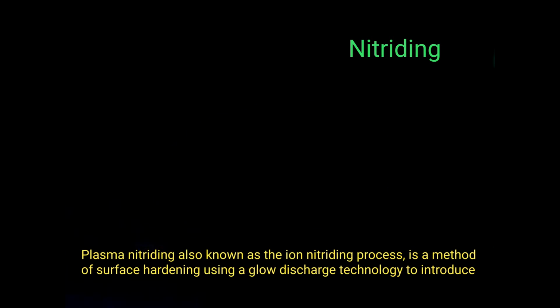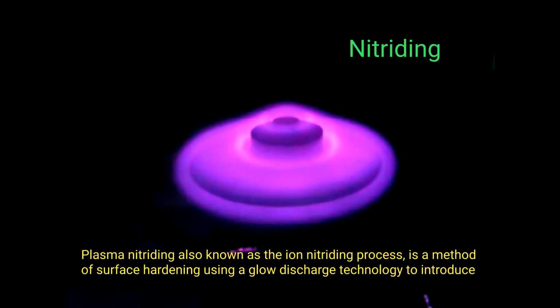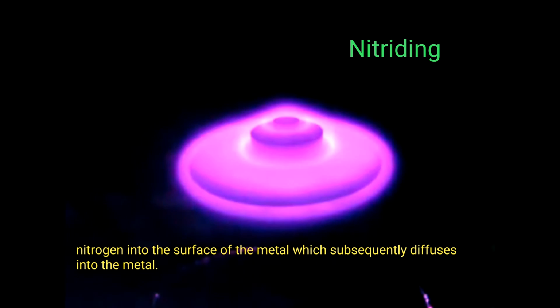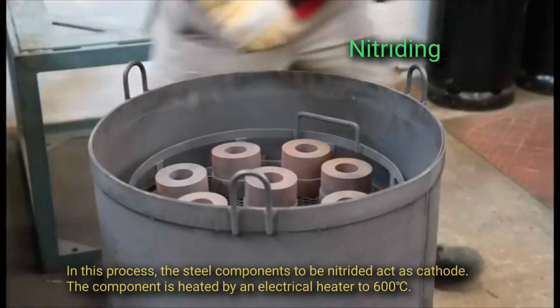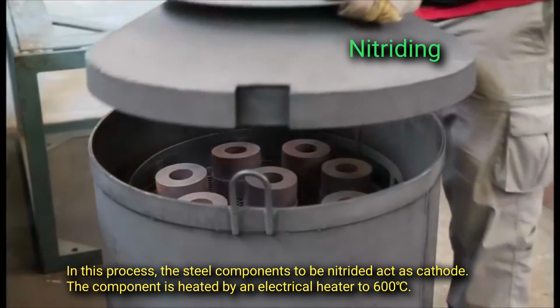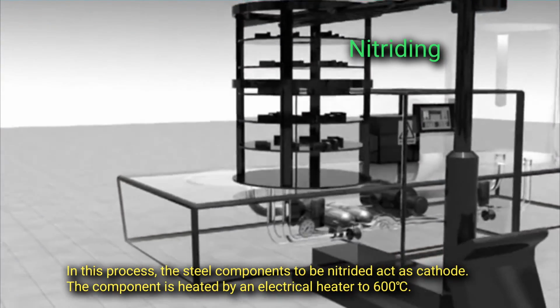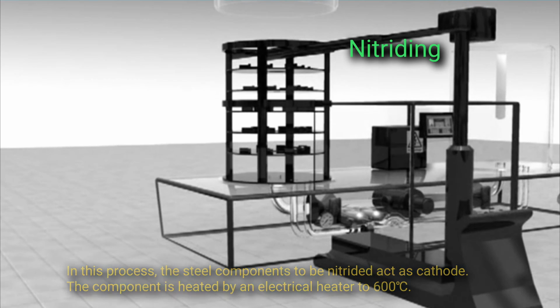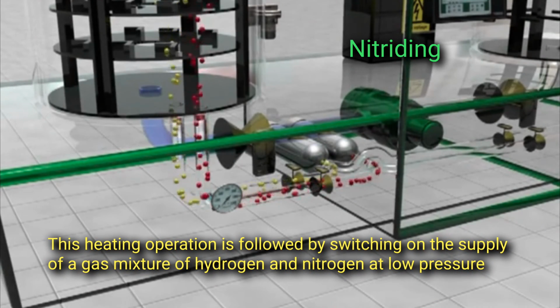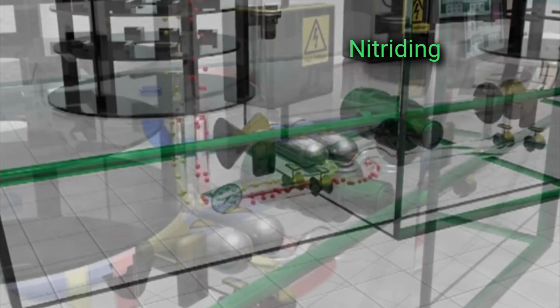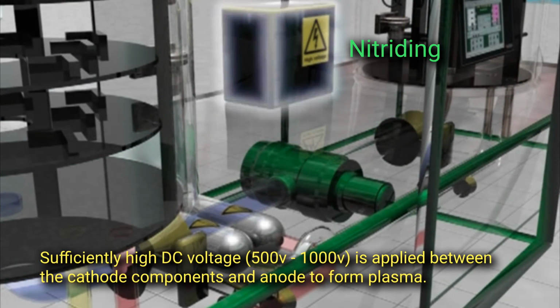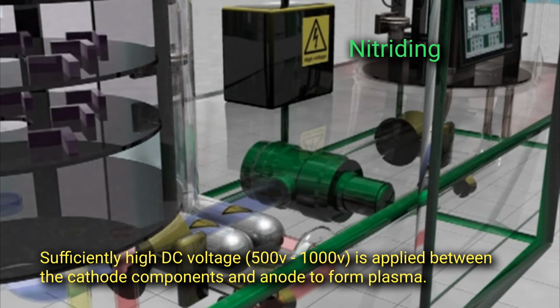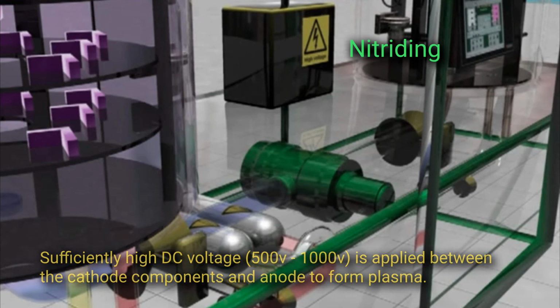Plasma nitriding, also known as the ion nitriding process, is a method of surface hardening using a glow discharge technology to introduce nitrogen into the surface of metal, which subsequently diffuses into the metal. In this process, the steel components to be nitrided act as cathode. The component is heated by an electrical heater to 600 degrees Celsius. This heating operation is followed by switching on the supply of a gas mixture of hydrogen and nitrogen at low pressure. Sufficiently high DC voltage, 500 to 1000 volts, is applied between the cathode components and anode to form plasma.